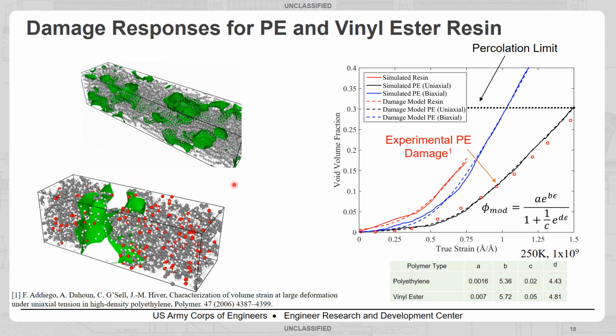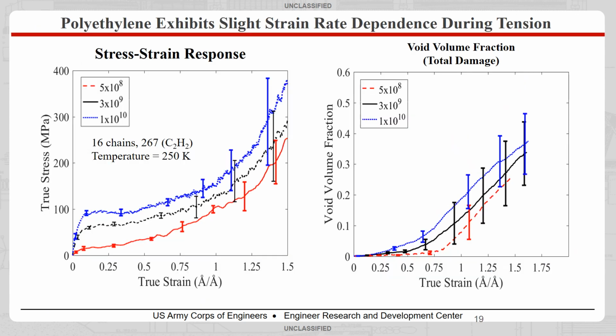So the experiments found that most of the damage occurs within the amorphous region of the semicrystalline polymer, which is why our simulations of the amorphous polyethylene do a very good job at capturing this type of void volume response. So we were quite pleased that our nanoscale simulations could capture this macroscale damage evolution, and we believe that using this model as a bridge from nanoscale damage to macroscale damage is possible. But before we do that, we have to look at the strain rate dependence